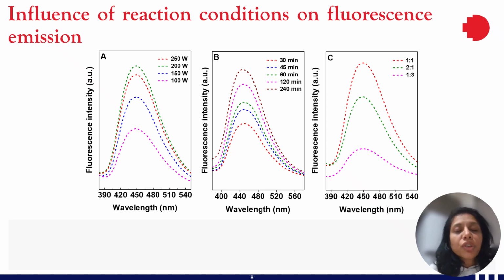And here we have changed the microwave power, reaction time, and glutamic acid and tryptophan ratio to see what reaction condition will yield the highest fluorescence. And we could see that when the microwave power was maintained at 200 watt for 120 minutes, and when the ratio was equal, we could see the maximum emission at 450 nanometer.